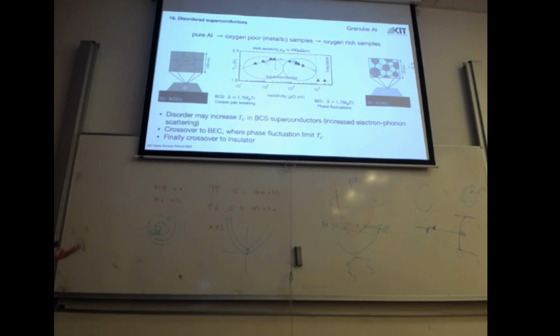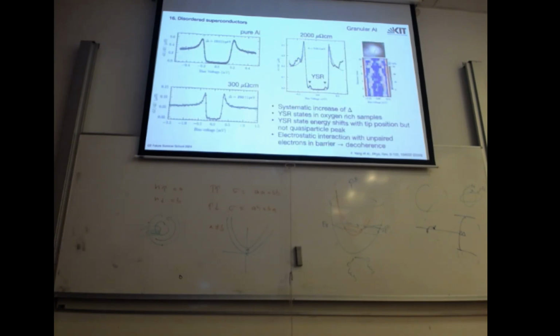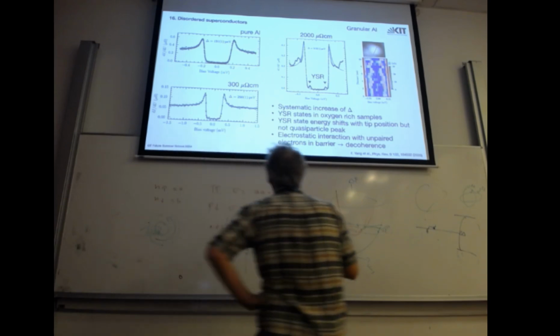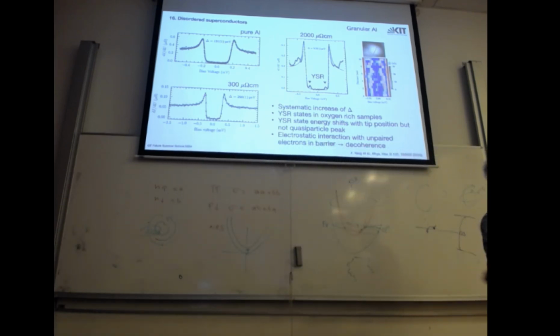But we have an STM, we can look at it. So the pure aluminum gap is here. We go with oxygen, the gap becomes larger indeed, and it still scales correctly. If we go slightly over the optimal point, the gap is actually maximum. But we see in-gap states.